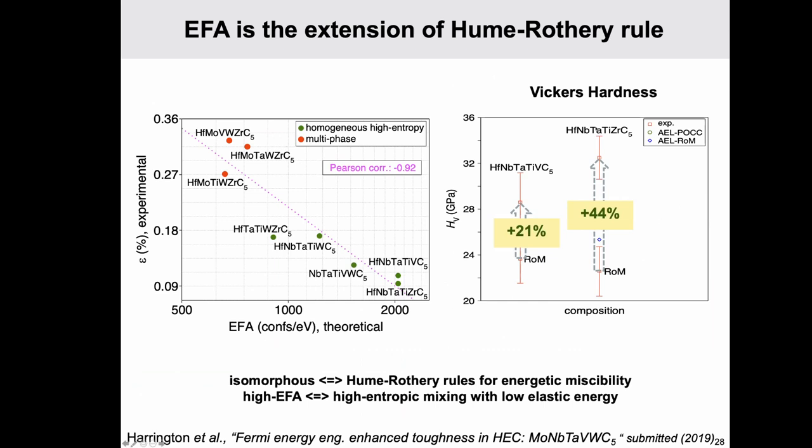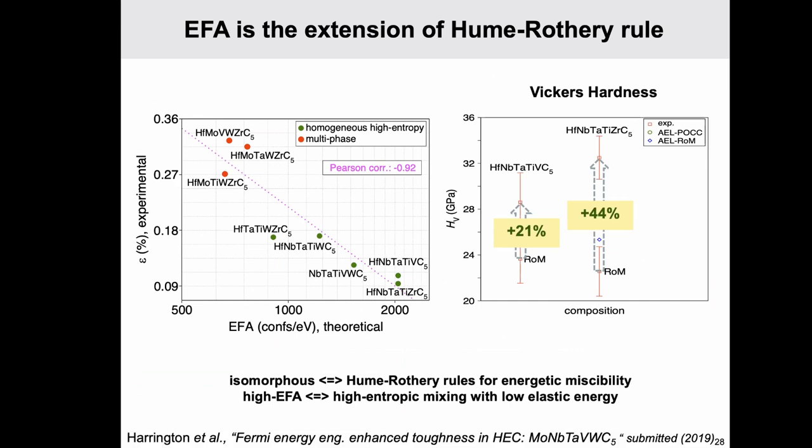In a non-homogeneous system, which means that all the positions are occupied randomly by one metal or another metal, the dislocation actually requires a different amount of energy. So maybe in this lattice, this position requires, well, let's say 50 millielectron volt. The other unit cell requires 75 and then 40, right? So all these energies are different. And as you know, when all the energies that are required and released to the system are different, you have problems of interference, you have problems of transmission, reflection of energy, and so on. So the overall effect, I just gave you an explanation that is really ideal, right? The overall effect is that a non-homogeneous system, a high entropy system, will require more energy to have the dislocation moving than the energy of the single compounds, because some of this energy is going to be reflected.